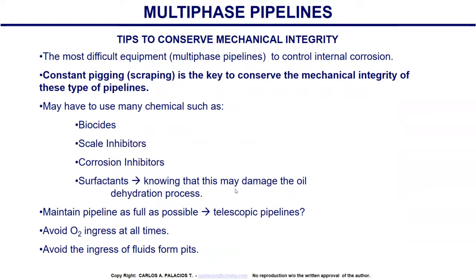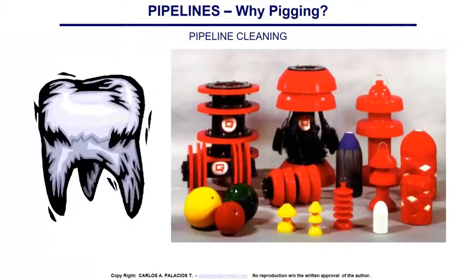Many chemicals: biocides, scale inhibitors, corrosion inhibitors, surfactants. Maintain the pipeline as full as possible. Avoid oxygen ingress at all times. Avoid the ingress of fluids from pits, meaning open pits with discarded oil. Pigging is the most important way to maintain the integrity of pipelines.